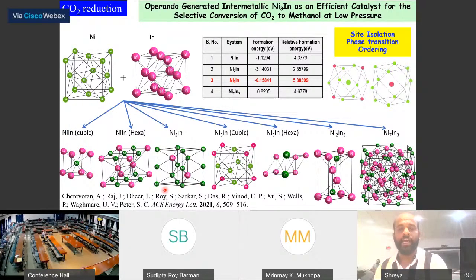I will talk about one example briefly. This is an example in the direction of CO2 reduction. This paper was just published a month back in ACS Energy Letters. Here, an operando generated catalyst, nickel 3 indium, is an efficient catalyst for the conversion of CO2 to methanol. When you take the metals nickel and indium and mix them together without understanding the solid state chemistry, you may end up with 1:1, 2:1, 3:1, 2:3, or 7:3. But you don't know exactly.